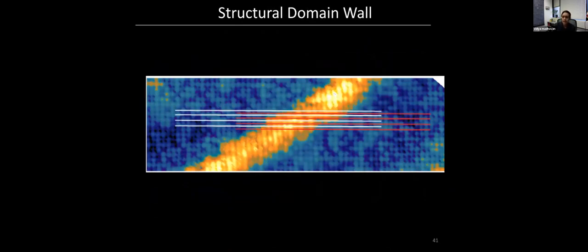To see that the atoms are shifted by half a unit cell, you have to zoom in, and you can either track the atoms by drawing lines, which is a pretty crude technique. But we've also done a more serious analysis using the phase of the Fourier transform. But essentially, whatever method you use, you can show that the atoms on the left side of this domain wall are shifted from the atoms on the right side of the domain wall by exactly half a unit cell. So this is exactly the kind of domain wall we're interested in.